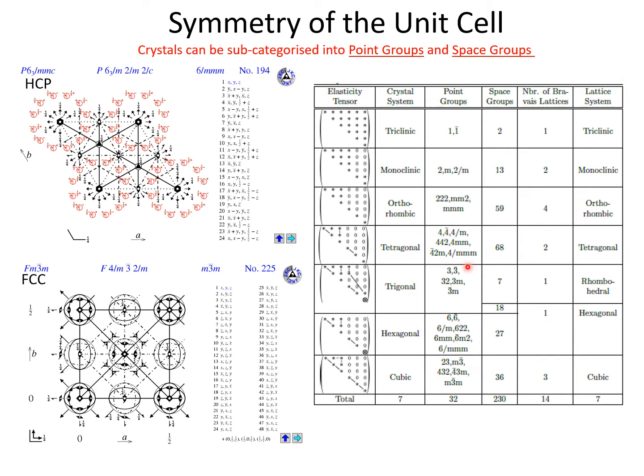But often a crystal structure has translations as well. It's not that simple. You can't just describe the structure in terms of simple symmetry elements, and you have to apply other elements. One is what's called a screw, which is a rotation plus a translation, or a glide, which is a reflection plus a translation.